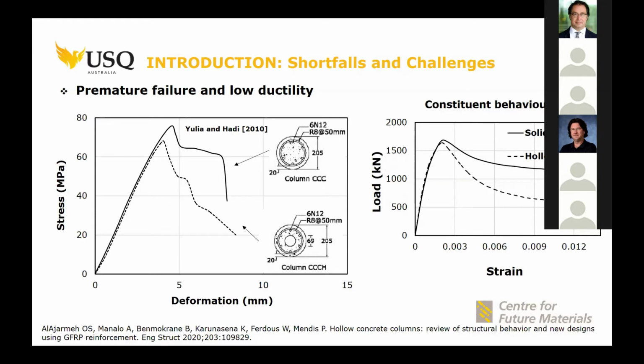And by telling that the reason is the confined concrete core, that means the confined concrete core is also related to something else, something related to the constituents themselves. We dug deep to see how the reinforcement is affecting that behavior, and we see that maybe the limited strain behavior of the steel, which has a yield strain, may affect that behavior.